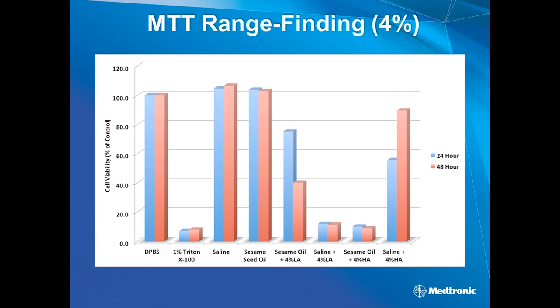So we were using 1% Triton X-100 as our positive control, and you can see obviously that we only have a cell viability level here of about 10%. So our positive control was very good at killing cells. And this is just the saline that we use. This saline over here is a buffered saline, and this one is not buffered. This is the 0.9% saline vehicle. This is the sesame oil vehicle that we used. And here we see that thankfully neither of our vehicles are causing any cell death, which is good.